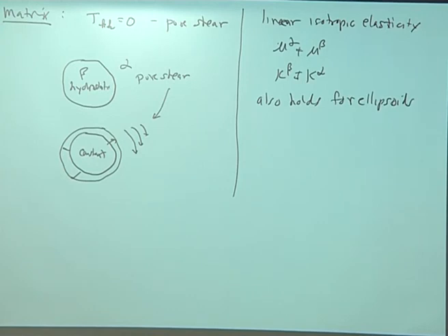So if you have a difference in elastic constants, you also get a constant strain inside the particle and a strain outside that varies. Kind of amazing. In ellipsoids, not spherical shapes, in ellipsoids. And this goes back to some work by Eshelby.